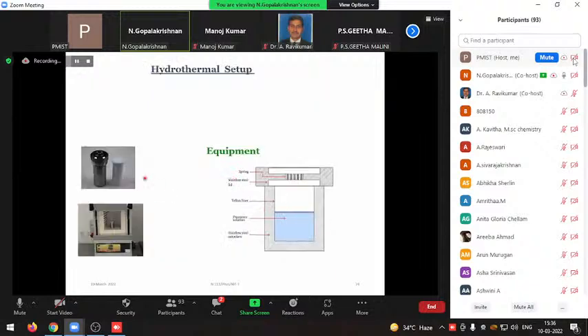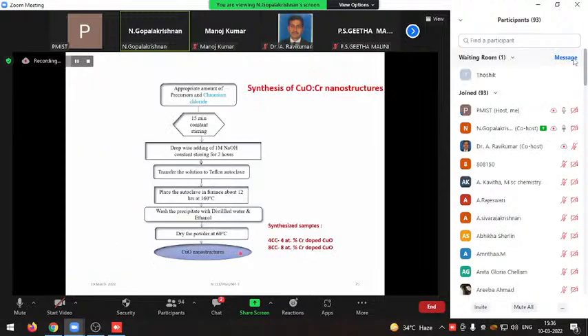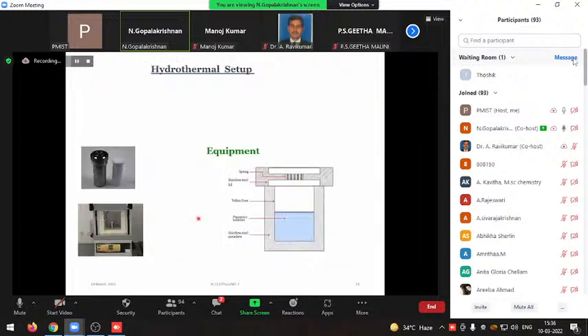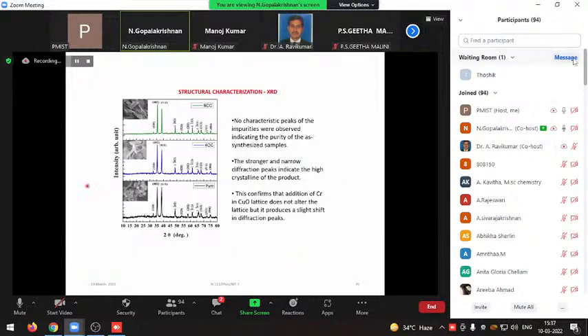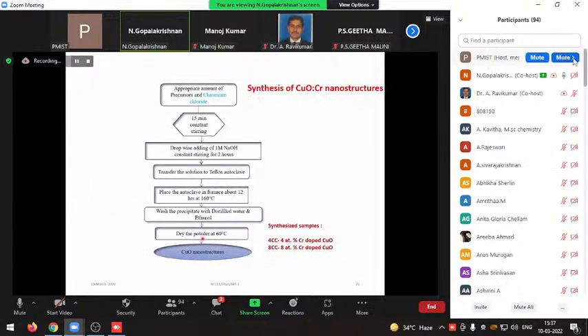This autoclave is kept in the furnace at the appropriate temperature. As shown here, it is kept in the autoclave at 160 degrees for 12 hours. Then the copper particles are deposited, precipitated here. Then we wash with distilled water and ethanol, and finally dry at 60 degrees. Then we get the copper nanostructure.